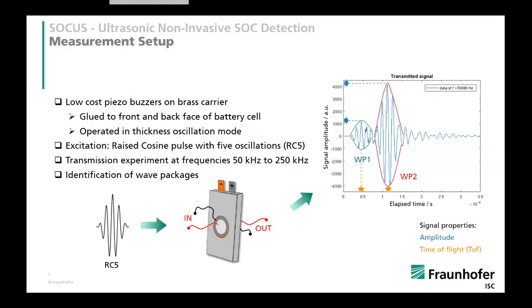In reality, we use far more complex procedures to analyze these waves. For instance, cross correlation of the wave, where you basically shift the excited and the transmitted wave on top of each other and integrate over the product of both waves. And the nice thing about these advanced measurements is that they are independent of the actual time of excitation and measurement, but only depend on the time delay between both signals. And for automated analysis of this data, these signal processing techniques are far more beneficial.